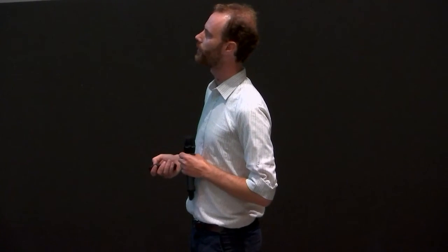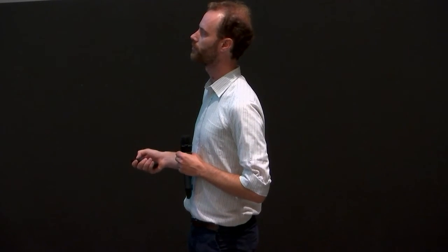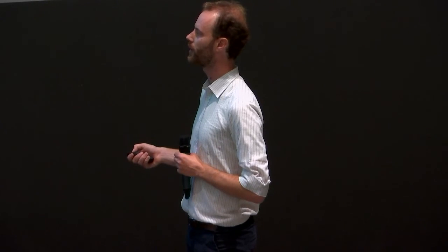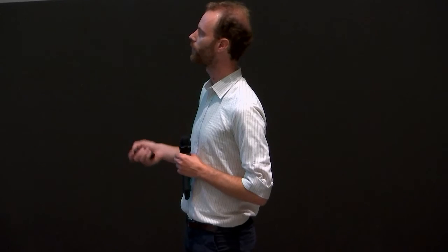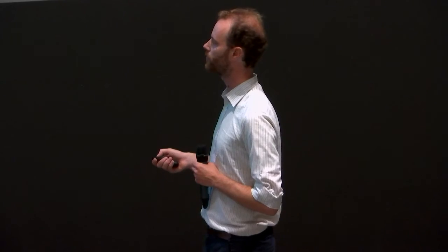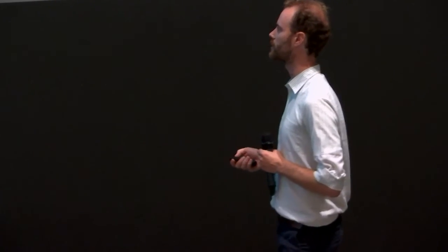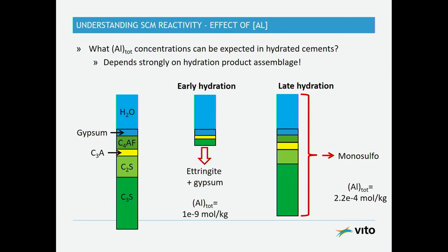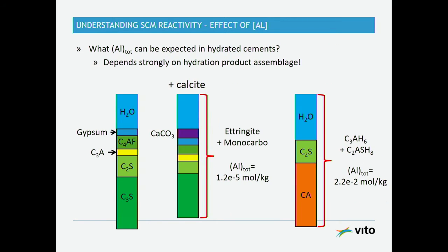For instance, in combination with cements, here we see if we start with this kind of a composition here, we have C3S, C2S, C3A, and so on and so forth. During early hydration, we mainly precipitate ettringite, and we have still some gypsum. Then we can get very, very low aluminum concentrations. At later hydration, on the contrary, when lots of our materials have reacted, as can be seen here, then we have, for instance, AFM, monosulfo, as the main hydrate, and then actually aluminum concentrations based on the solubility products and the other cations in the solution might be much higher.